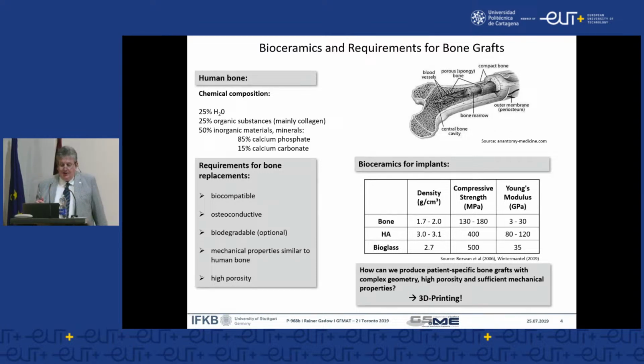The density we are talking about, because of the high porosity, about a lightweight material. The density is between 1.7 and 2 grams per cubic centimeter. And this is the natural bone. So the hydroxyapatite, which is the synthetic bone material in pure phase, has a higher density, 3 to 3.1. The bioglass comes closer to the natural bone. But you see, if we look to the compressive stress, and here we compare the best compatible materials that are available, we always have a much higher mechanical strength for the hydroxyapatite, HA, and for the bioglass compared to the natural bone.